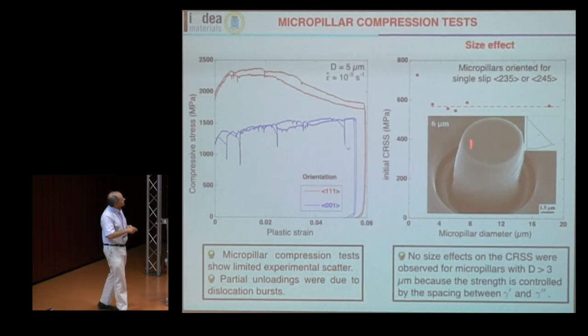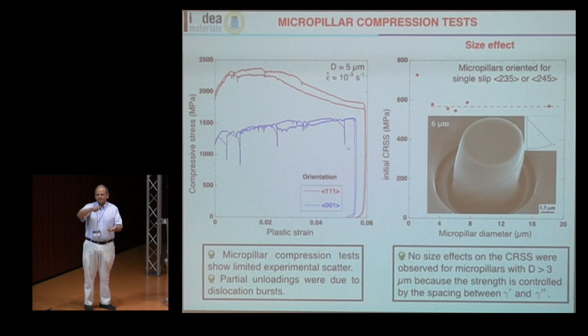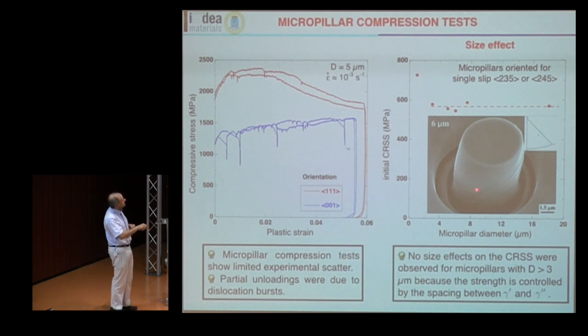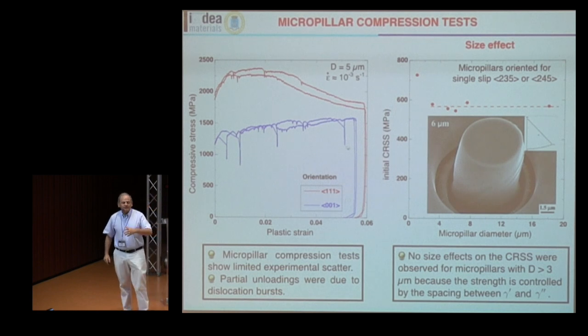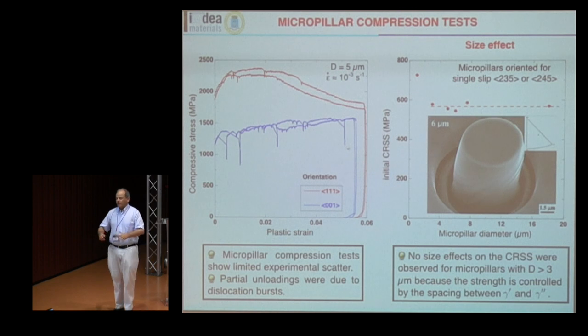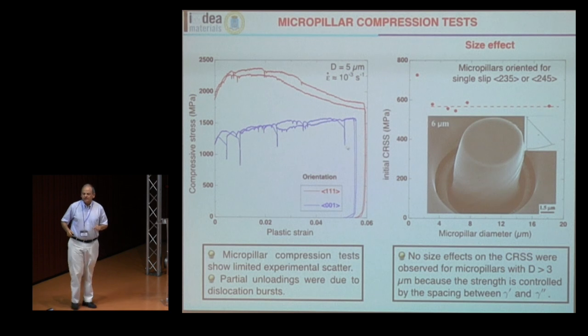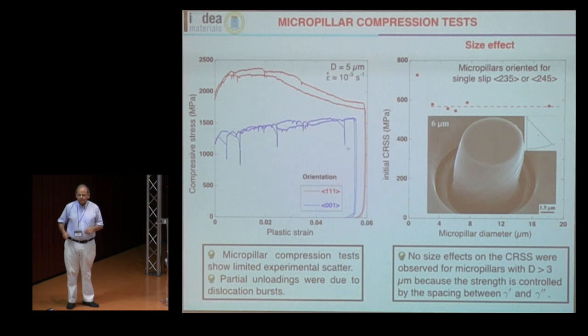We milled micropillars from 1 micron to 17 microns in diameter — this largest micropillar costs a fortune. We carried out micropillar compression tests oriented for single slip. You can see the slip bands, and you see that from about 3–4 microns onward, the critical resolved shear stress remains constant. This is critical because what controls the strength of this material is the distance between the precipitates, which is on the order of 20–40 nanometers — we are at 5 microns, two orders of magnitude higher. So we are getting the bulk properties. These are the good news for this complex material.